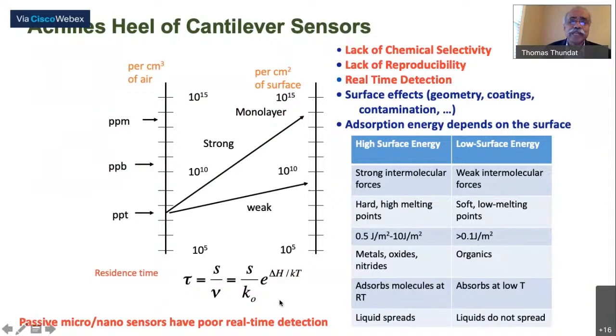Depending on the interaction energy, so delta H, the heat of adsorption, you can have a monolayer of material. So there is a big concentrating effect by the surface. Now this is in concentration per centimeter square. Another issue is the reproducibility, which I will come to again a little later. And the third one was the real-time problem, because the cantilever itself is extremely small. So the passive nano sensors and nano devices will have trouble with real-time detection, because if your molecules are coming by diffusion, it is going to take a long time to reach the surface.